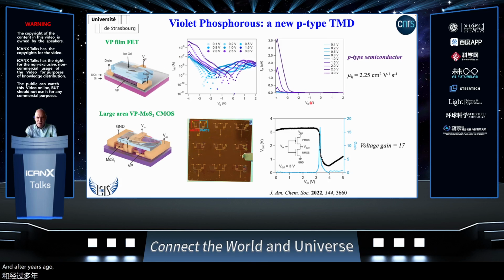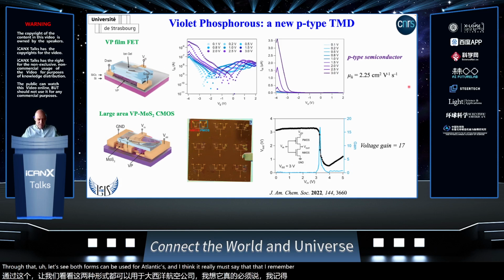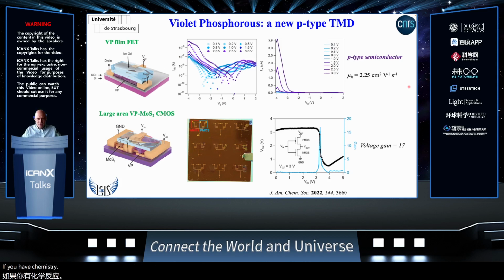And as a proof of concept, making use of the fact that we have developed a p-type material, we fabricated a CMOS-type device, combining an n-type, MoS2, and the violet phosphorus p-type, and we obtained a voltage gain as high as 17. So that was the first proof that violet phosphorus can be used for electronics. And I think it really demonstrated that there are a number of potential new materials that can be created. And here as well, we need the creativity of chemists to try to develop new materials using a typical type of composition.